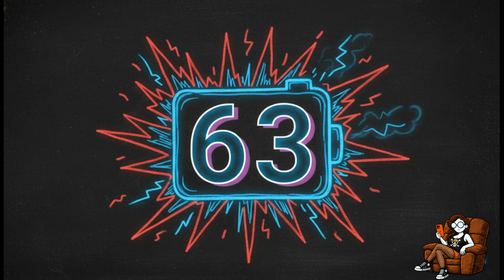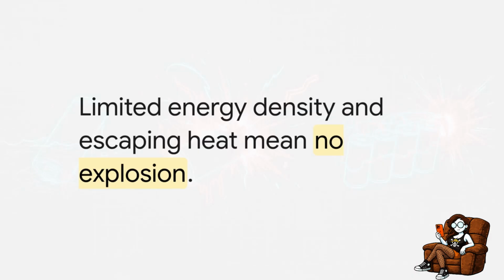And because of those insane currents running through that small cylinder, the internal temperature climbs with terrifying speed, shooting straight up to 63 degrees Celsius in almost no time flat. You're sitting there expecting the safety vent to pop, you're bracing for the fire. But then it inexplicably stabilizes. No venting, no explosion, nothing. So why did it survive?